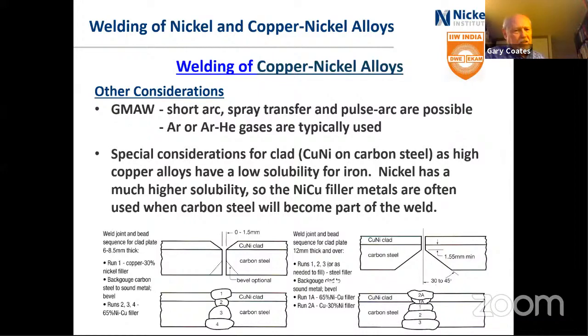Special welding conditions have to be done because the copper alloys, high copper alloys, have a very low solubility for iron. So if you get some contamination of the carbon steel into a copper nickel weld, you have problems there. So you have to make sure that you are not getting carbon steel into the weld where you're using the copper nickel filler metal. And sometimes the nickel copper filler metals, where the nickel has a much higher solubility for iron, are used in that joint where you're attaching the two together, where you will get carbon steel pickup there.